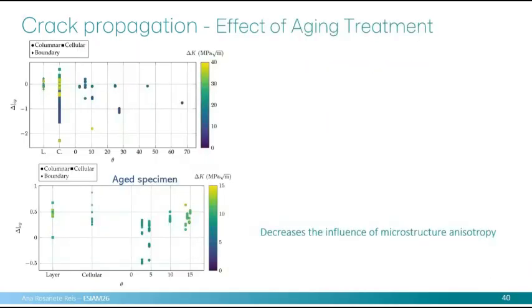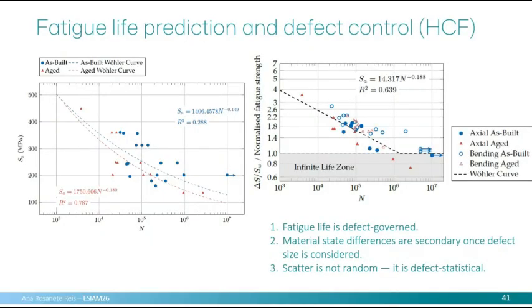Then the maraging, as you know, is a material that we usually need to treat. We did the heat treatment, and after that we understand that the anisotropy is lowered. So this is a good thing. But then when you go to fatigue life prediction, one conclusion that was not so evident is that the heat treatment doesn't improve the fatigue life. So this was one thing.